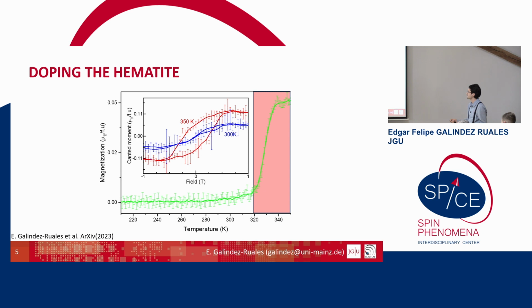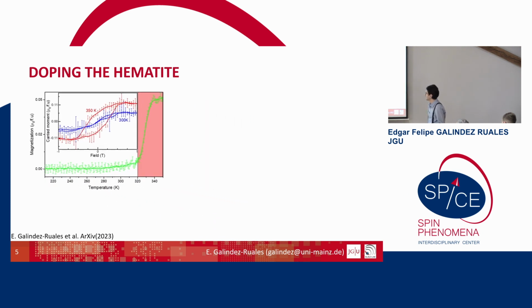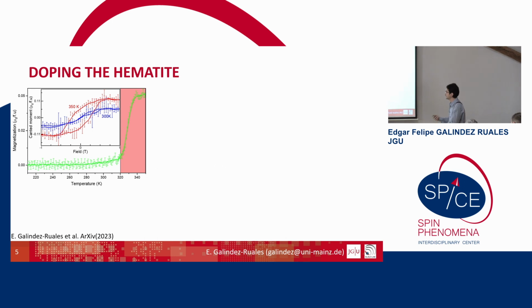When you are at low temperature, or at room temperature in the easy axis phase, you don't have any hysteresis loop. You have a small contribution in the canted moment, and this we explain and blame on a gamma phase, another phase of the iron oxide that always nucleates between the substrate and the thin film. Then we say, okay, we have saturation in the magnetization, so we don't expect any contribution other than the bulk contributions, in theory. We are just adding dopants to push some electrons to the conduction band, so we can measure something, right?